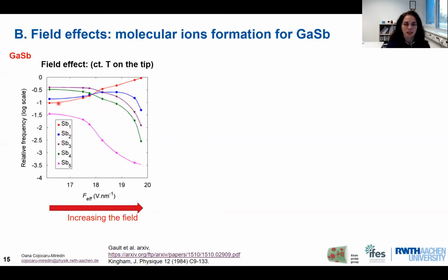And the fraction of these molecular ions can be increased or decreased based upon the applied field. So if we increase the field, the fraction of these molecular ions progressively decreases, while the antimony single ions are increasing. So there is definitely a strong relationship between the presence of the molecular ions and the field.